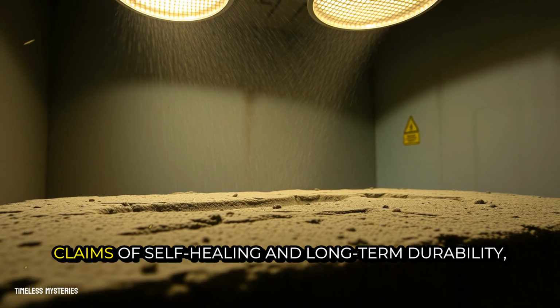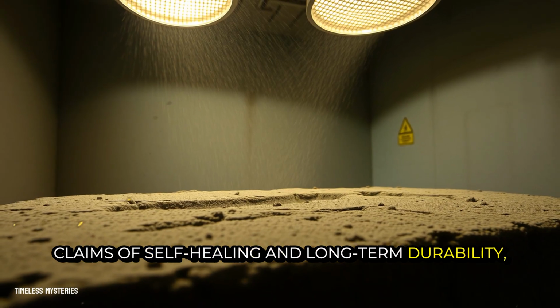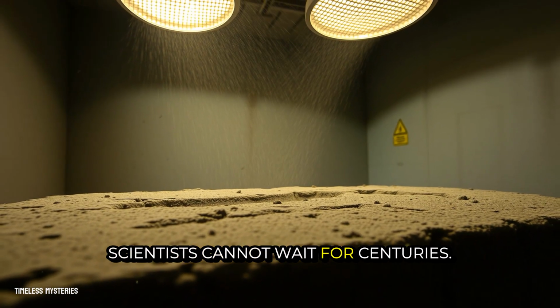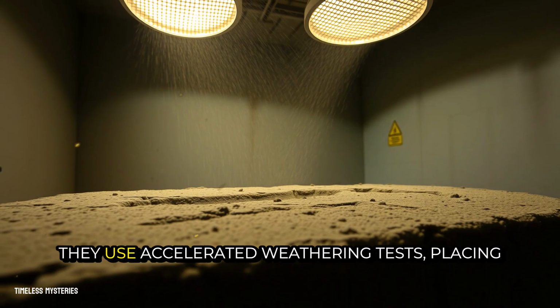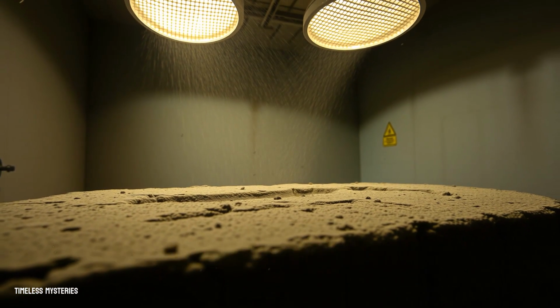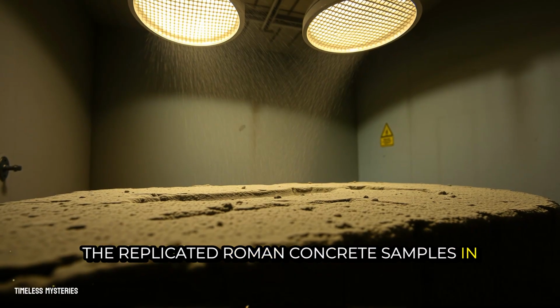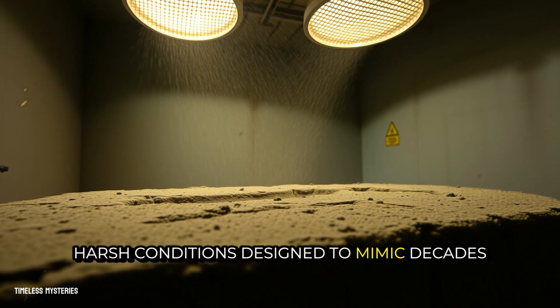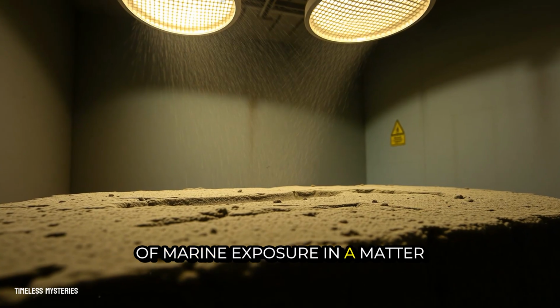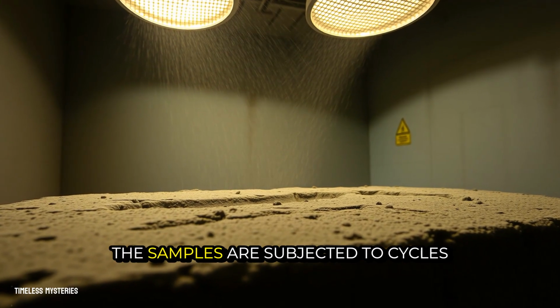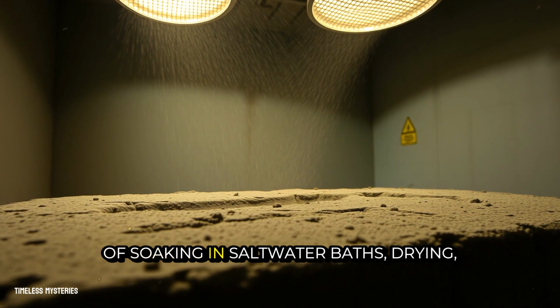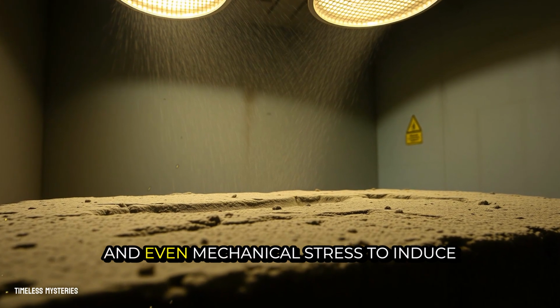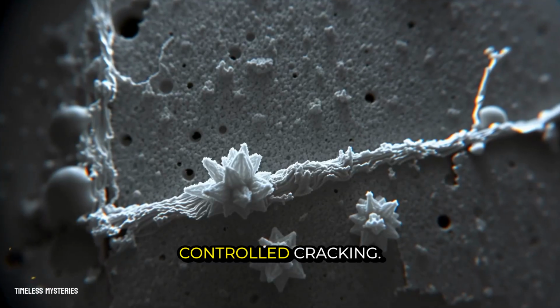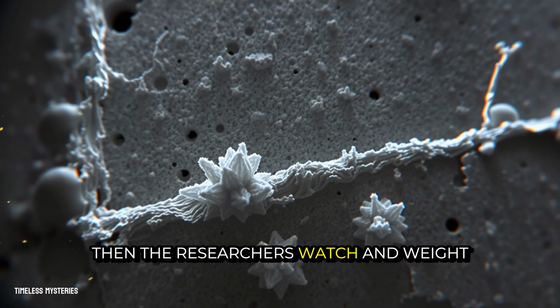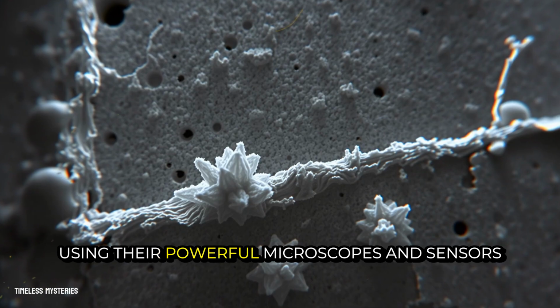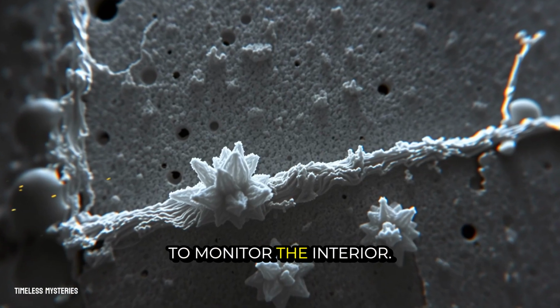To test the claims of self-healing and long-term durability, scientists cannot wait for centuries. They use accelerated weathering tests, placing the replicated Roman concrete samples in harsh conditions designed to mimic decades of marine exposure in a matter of months. The samples are subjected to cycles of soaking in saltwater baths, drying, and even mechanical stress to induce controlled cracking. Then, the researchers watch and wait, using their powerful microscopes and sensors to monitor the interior.